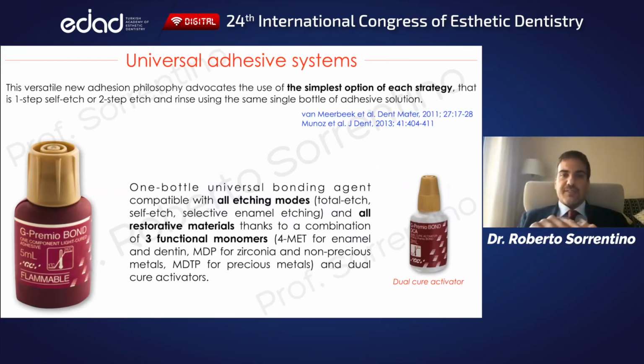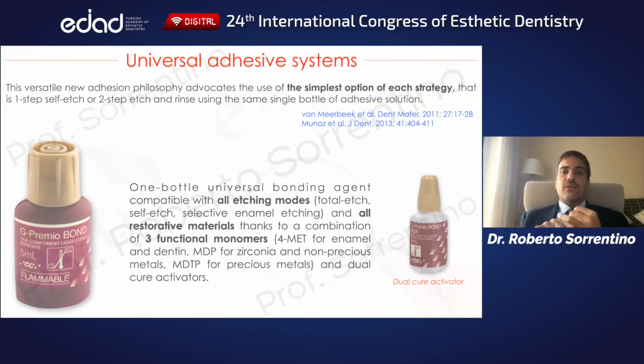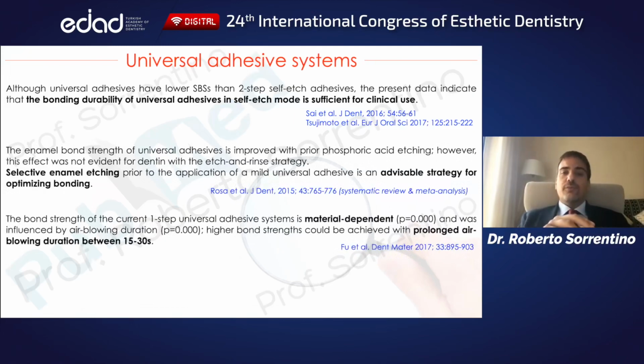If we look at the most recent literature regarding the universal multimode adhesives, it is clear that their bond effectiveness is satisfactory for clinical use, that the use of the selective enamel etching technique can be useful to increase long-term durability of the adhesive complex, and that the bond strength of multimode adhesives is dependent on the brand.